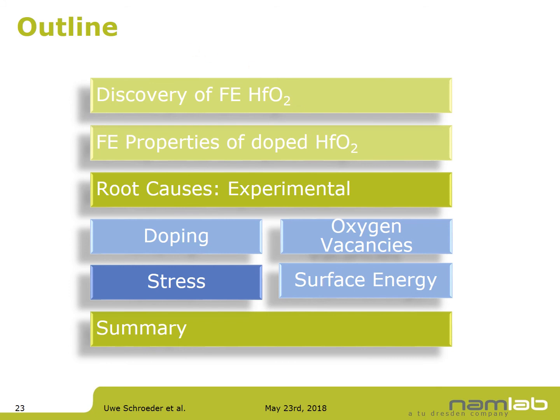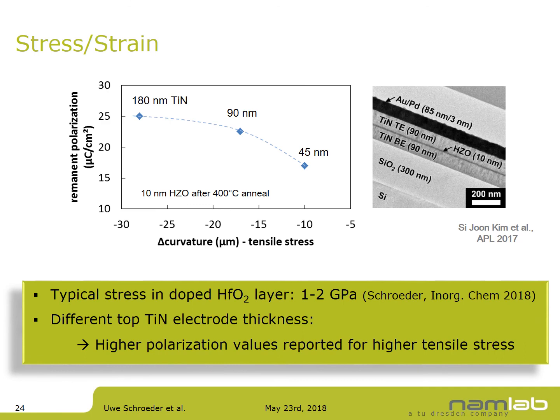The third root cause is stress. Measured stress in hafnium oxide layers is in the order of 1–2 GPa. Work from the University of Texas at Dallas and Professor Kim's group showed that increasing the top titanium nitride electrode thickness from 45 to 180 nm increases tensile stress — measured via film curvature — and correspondingly increases the remnant polarization. Stress appears to be an important factor in improving the ferroelectric properties of the layer.